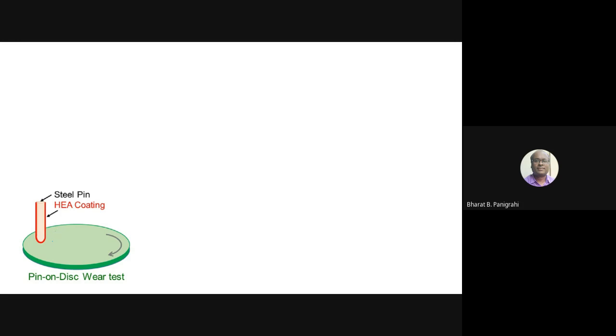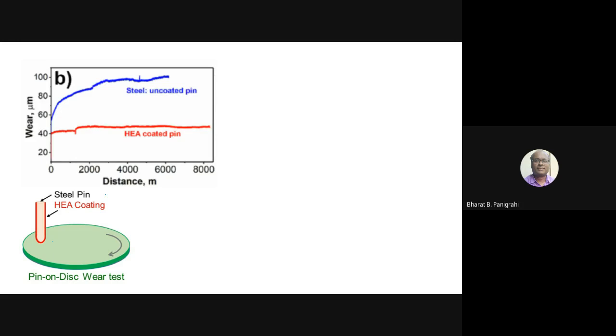And when you see their profile, you can see there a material which is uncoated pin, and this y-axis shows the wear rate. It shows a huge wear. But when you have a coating, you see that the wear has almost dropped. It says that whatever coating you have done has a very good wear resistance. There is a significant drop in the wear behavior.